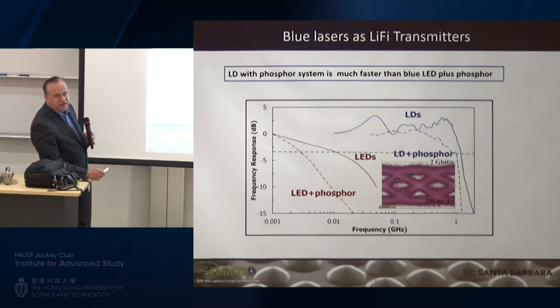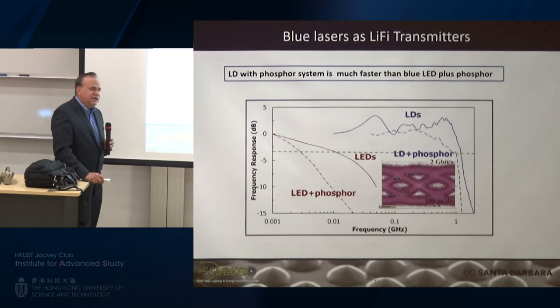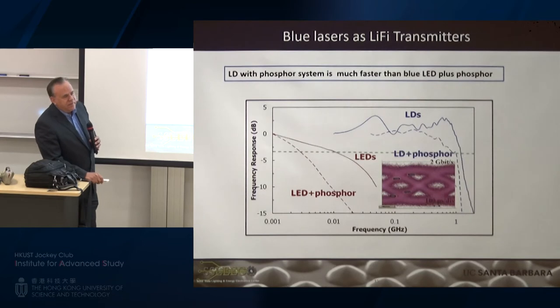but what they don't tell you is that's not in a light bulb configuration. I'd like to ask Patrick one question: what's the current speed of an LED light bulb? If you look at the analog band without the yellow phosphor, maybe about 10 megahertz, but with the phosphor it's about, at best, 5 megahertz. Okay. So if you do Nyquist, at best it's 10 megabit per second, but usually below that. Yeah. So it's moved up a little bit, but not much.